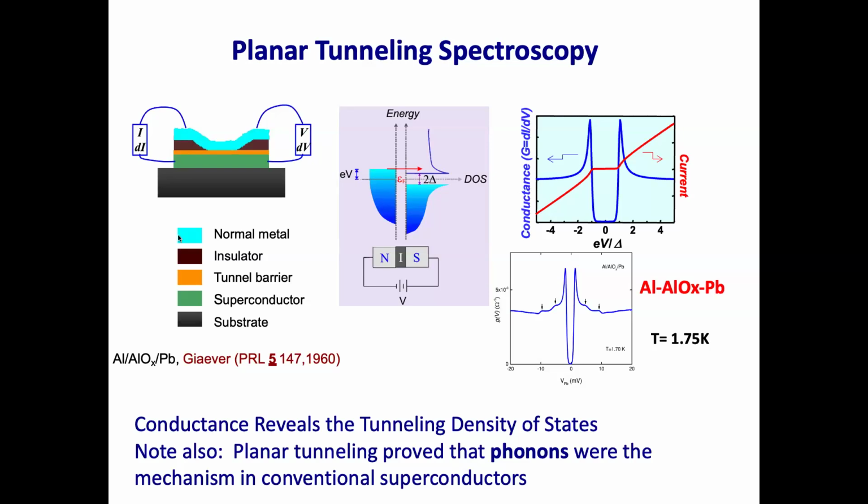So in the BTK theory, and we've done a bazillion junctions, if you have a very, very high transmittance junction, then you see the Andreev peak. If you have a low transmittance junction, like a thick barrier, then you don't see an Andreev peak. The probability of Andreev reflection goes down quite a bit. It's right there in the theory. And so you go from point contact to tunneling, for instance. You go from Andreev reflection to tunneling, depending on the transparency.